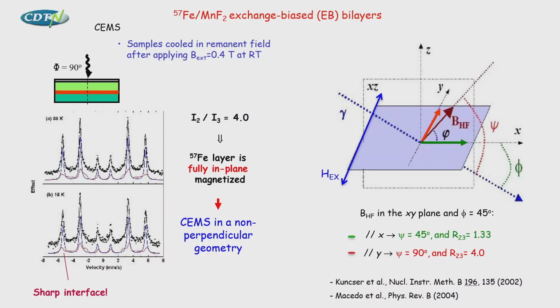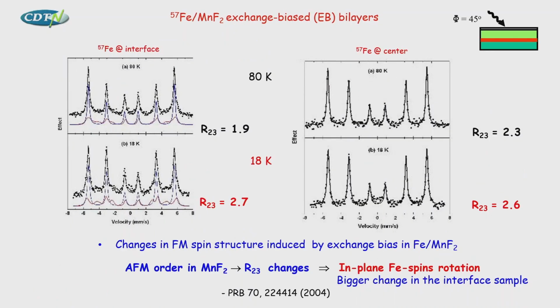Okay. This is what we did, and you can see that as soon as you go down with the temperature, okay, you get the antiferromagnetic order, and you see the change in the lines intensity. That means you really see that even in remanence, the coupling at the interface causes a change of the spins, of the iron spins in the plane. And you see also that the change is bigger at the interface, okay? This is what we did in the beginning.